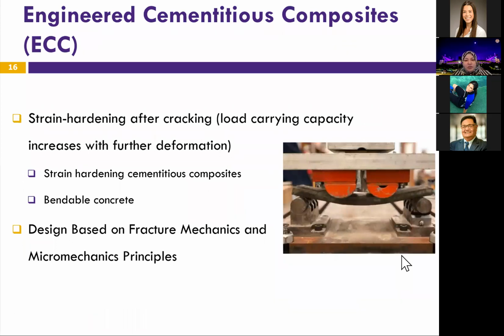So ECC is not new. It was developed about a couple of decades ago by Dr. Victor Li from the University of Michigan. The main advantage of ECC compared to concrete is that it exhibits pseudo-strain hardening after cracking. This leads to an increase in load carrying capacity with a significant increase in deformation, which allows us to produce bendable concrete like you see right here in this picture.